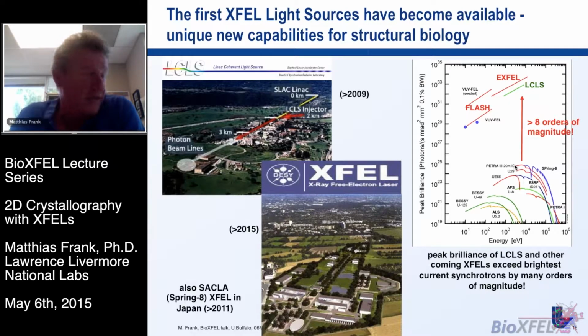And it's not that the FELs produce, on average, more photons than these synchrotrons, but they produce photon pulses that are much shorter. Because the pulse duration is in the denominator of the peak brilliance, the peak brilliance goes up as the pulse duration goes down. So we're talking about 10 to the 12 photons in a 1 micrometer spot in some tens of femtoseconds.